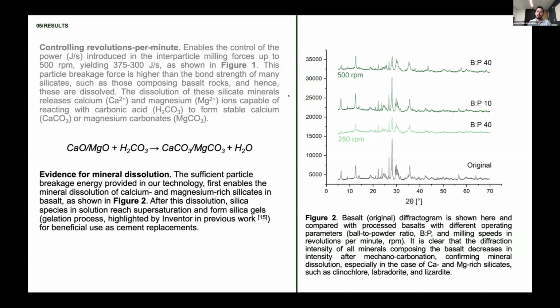So that's great. But what that also does is that as these silicates dissolve, the silica that is dissolving is going to go through a polymerization and gelation process, which really just means that that silica is going to agglomerate and create a gel that we hypothesize, and we show, can be pozzolanic.